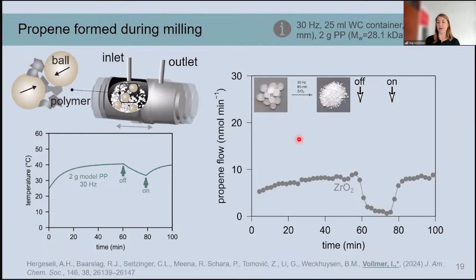And this is also visible from the fact that for the thermal conversion, we need temperatures above 250 degrees, while in this case, we do not even exceed the melting point of the polymer, seemingly, as we still obtain a powder that doesn't show much sign of melting. And the temperature, at least measured on the outside of the container, also does not exceed 40 degrees Celsius.